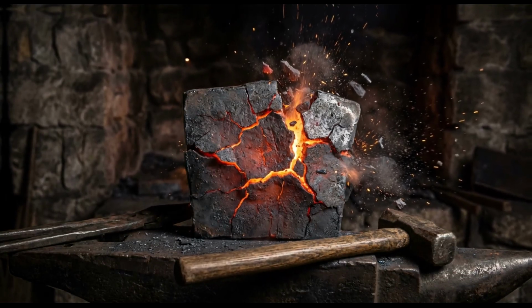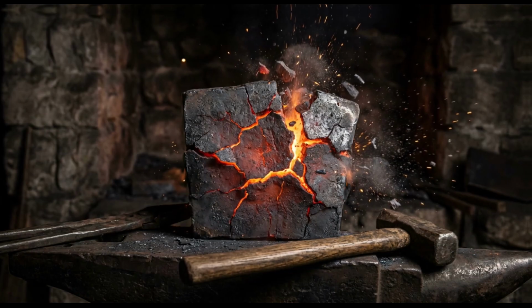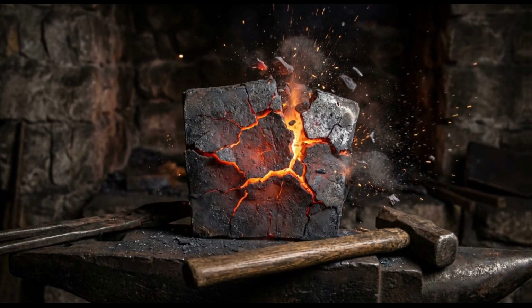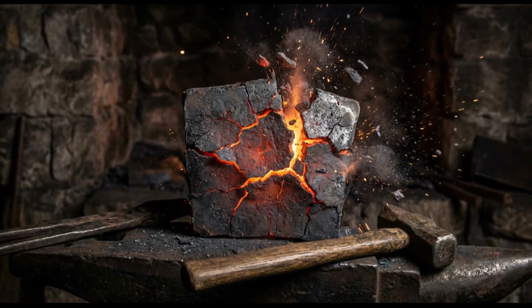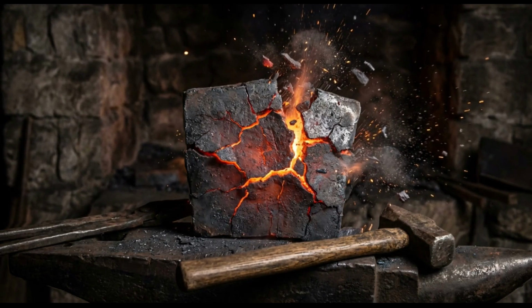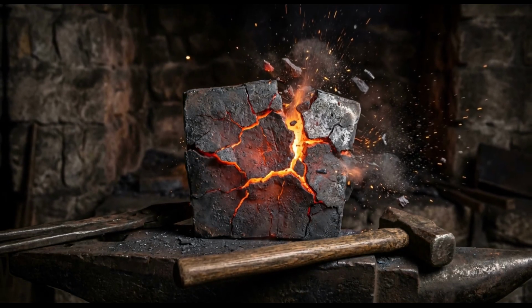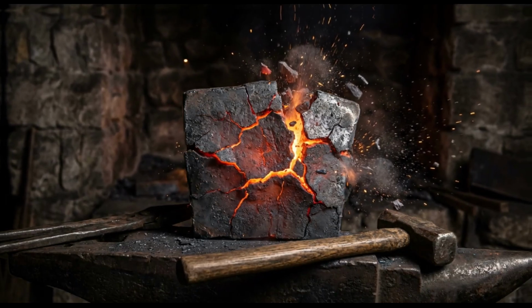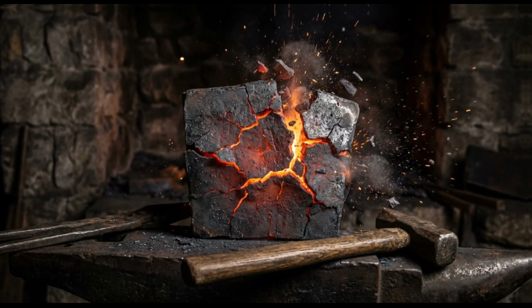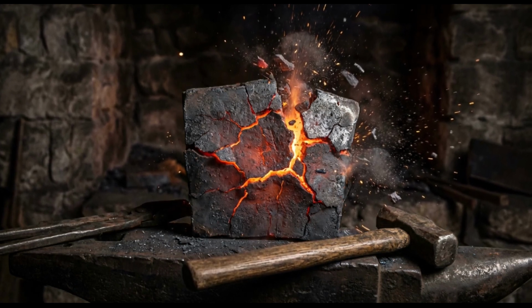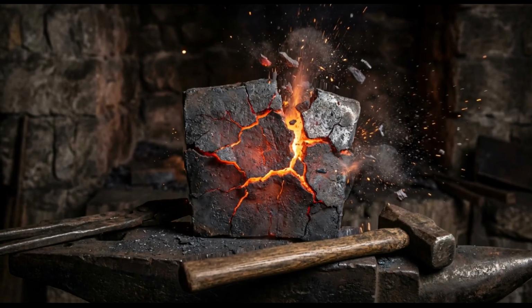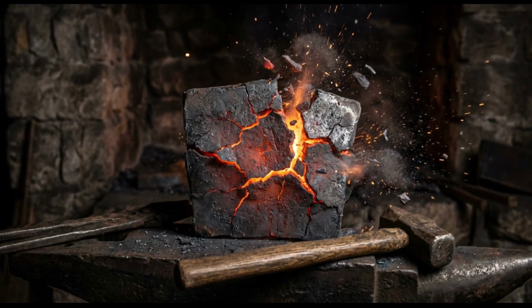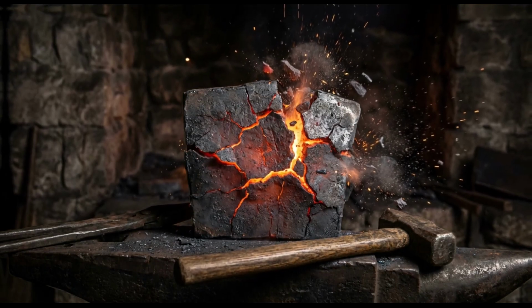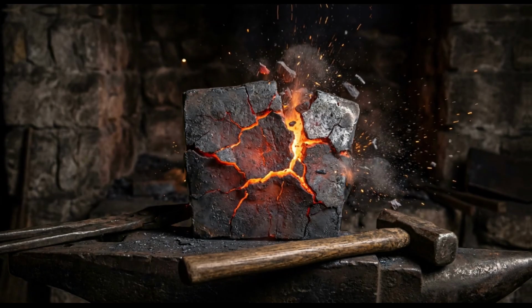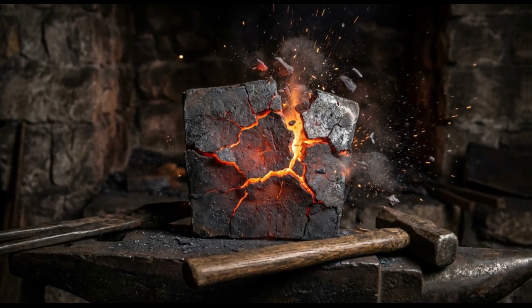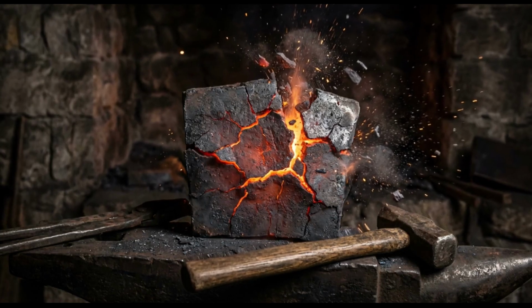The narrator's insightful eye, like a modern microscope in the sterile bluish light of the laboratory, focuses on the dramatic grain structure of the steel, where instead of fine, smoothly woven together fibers, you can see huge, thick, and brittle carbon crystals trapped in a dead matrix of iron. The surface of the crack sparkles in the orange firelight like a rough, impure diamond, revealing the merciless truth of the sword's architecture. It was as hard as glass and just as brittle. Erik's finger, calloused and black with soot, slowly traces the sharp, jagged edge of the fragment, feeling every microscopic irregularity, every evidence of brutal haste and bravado.